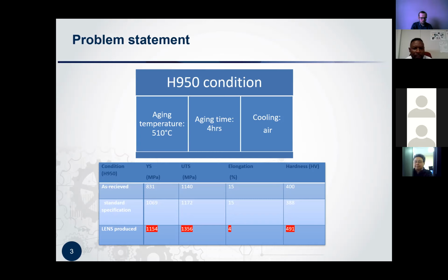An H950 condition is an aging condition for 17.4 PH stainless steel, where you subject your material to 510 degrees for 4 hours, followed by air cooling. When we applied this type of condition to the 17.4 PH produced through the lens or DED platform, we found that the mechanical properties were way off. As you can see here, we requested a sample from that side so that we can do our own characterization, and it's named as received. At the bottom are the mechanical properties for the lens produced. You can see they are way off compared to the as received. These results are the ones which prompted this study.